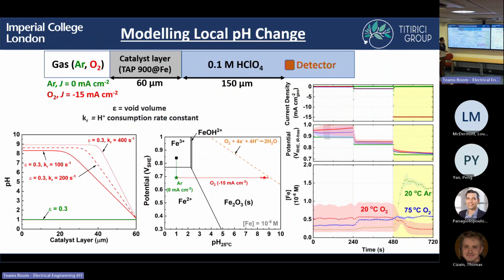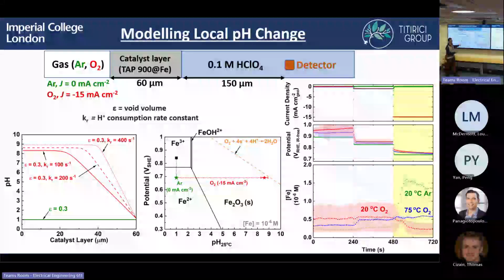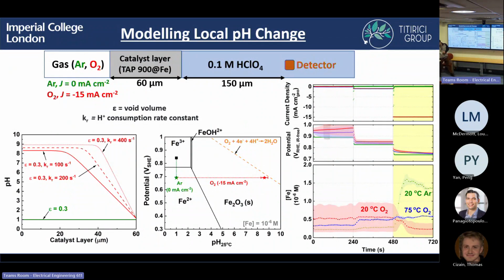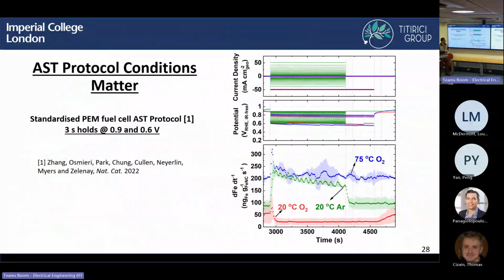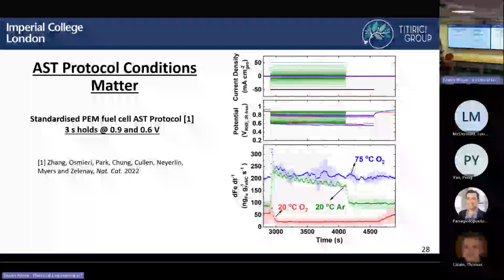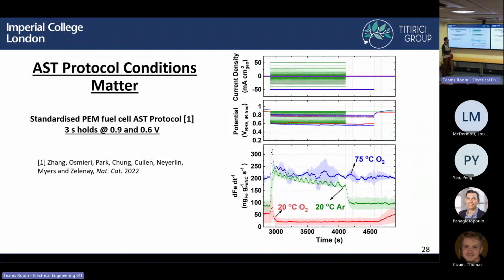And so if we again look at the Pourbaix diagram at 25 degrees, we see in argon, we're just stepping down in potential from iron 3+ to iron 2+, whereas in oxygen, depending where you are in the catalyst layer, you're either in a pH around 1 at the interface, but as you go into the bulk, you're in this region of iron oxide formation. And another thing I wanted to add is the AST measurement. We saw that there's very clear differences depending on the conditions of that protocol. And so it's really important to consider that basically every condition that you have completely changes what you'll see afterwards in the catalyst layer.